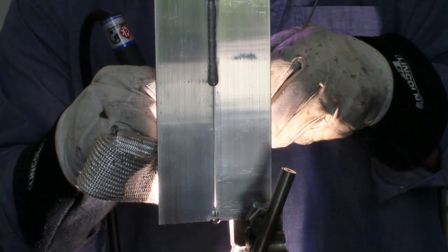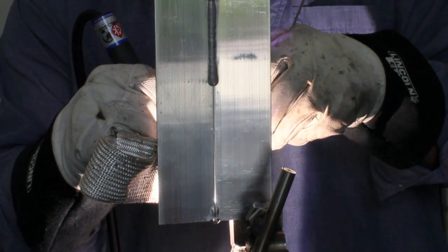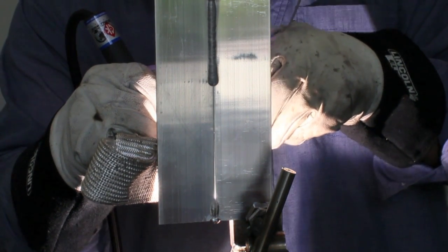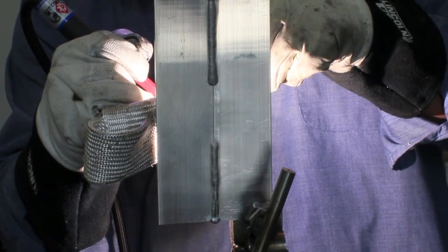See on the bottom here, I'm a little too gingerly, wanting not to melt that tack away, and for the first quarter inch or so, you see it kind of left that line, didn't quite penetrate, and that is always an issue with aluminum joints like this. But what you want to do is step ahead roughly 1/8 inch and pause while you add rod, and you want to do that about once a second.